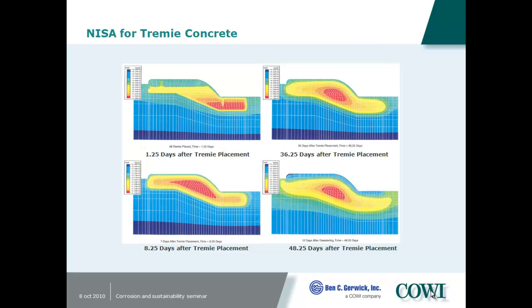This is after one day. All the Tremie is not in place even after the end of one day, so this is already starting to hydrate down here by the time we're up to the top. So you can see normally it cools around the perimeter while it's still heating and expanding on the inside. So it expands on the inside, then it creeps, and then when it cools, it pulls back in,